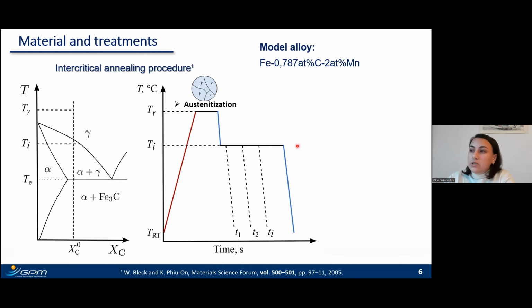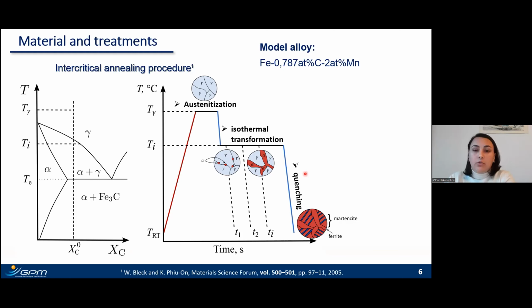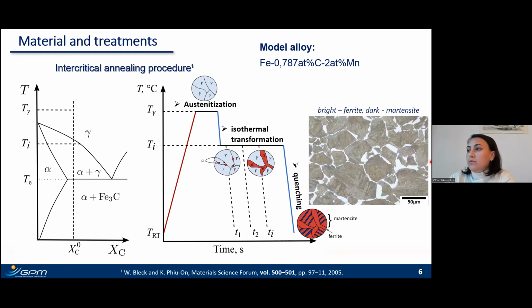In this stage, the austenite to ferrite phase transformation takes place, and depending on the parameters, a different mixture of ferrite and austenite microstructure will be obtained. Then during the quenching to room temperature, the remaining austenite transforms to martensite. So in the end, we will obtain a ferrite-martensite microstructure. An example of the micrographs you can see on the slide. Here, ferrite is shown in bright contrast and martensite is dark.